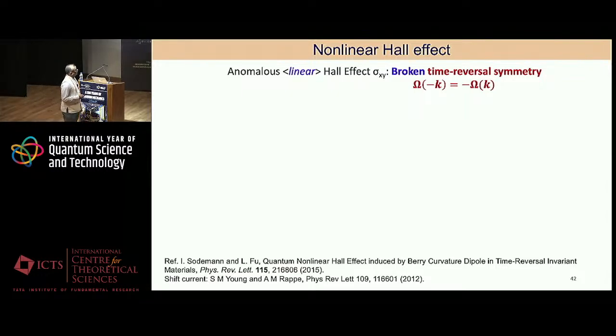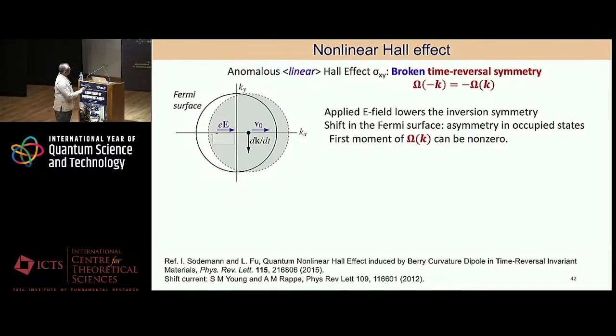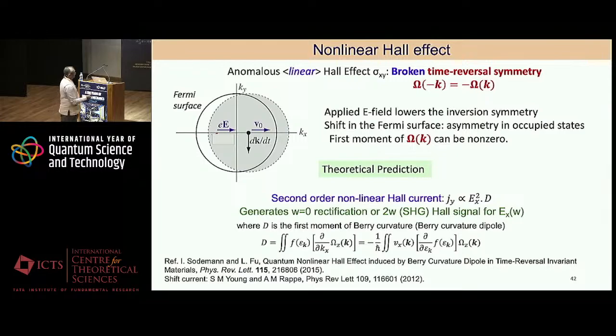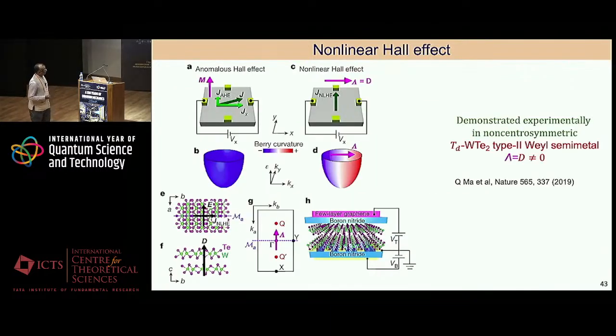The nonlinear Hall effect basically relies on the fact that when you apply an electric field along the x direction, it creates an asymmetry in the Fermi surface due to a shift in k space along the x direction, and that can give rise to effects related to the first moment of the Berry curvature. That's what was shown by Liang Fu and Inti, that the Berry curvature dipole, which is defined like this as shown by Mandar, gives you the anomalous nonlinear Hall effect Jy, which is quadratically dependent on the electric field Ex, and the proportionality constant is given by the Berry curvature dipole. Yeah. And that's basically the key thing in the spectroscopy that we are going to propose.